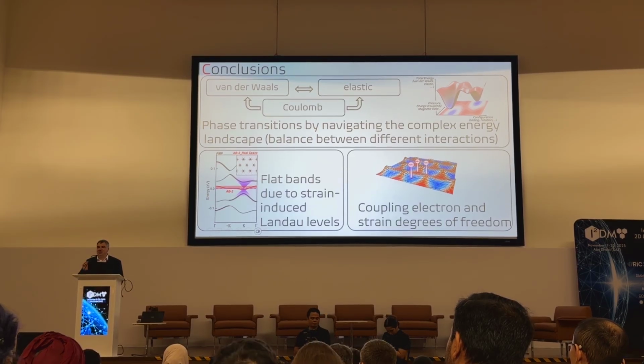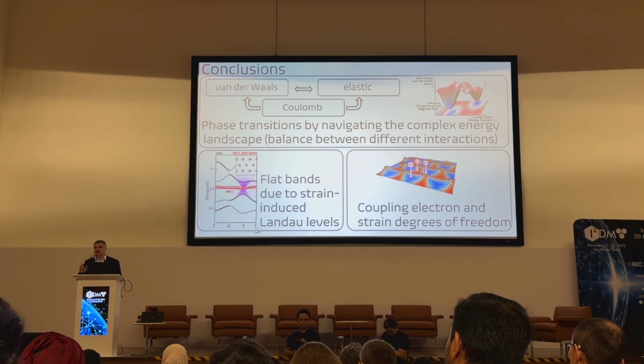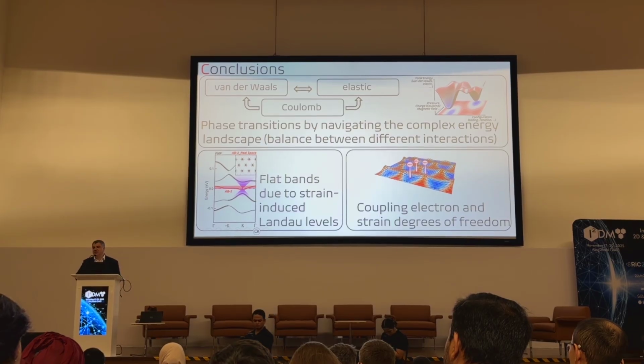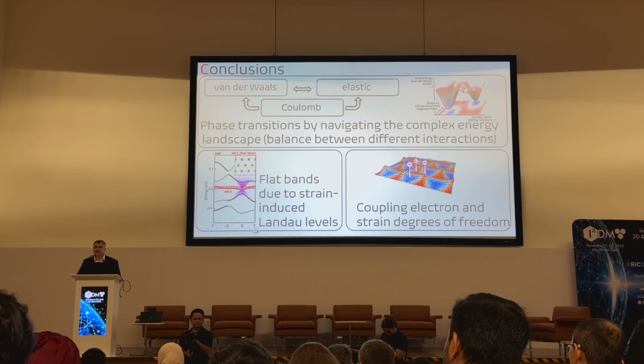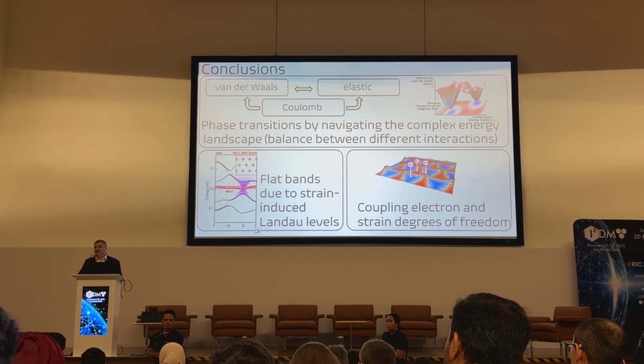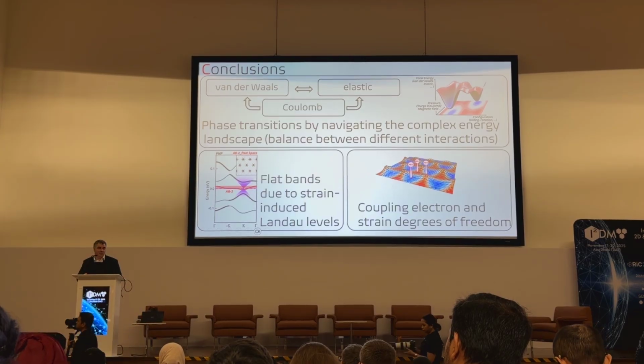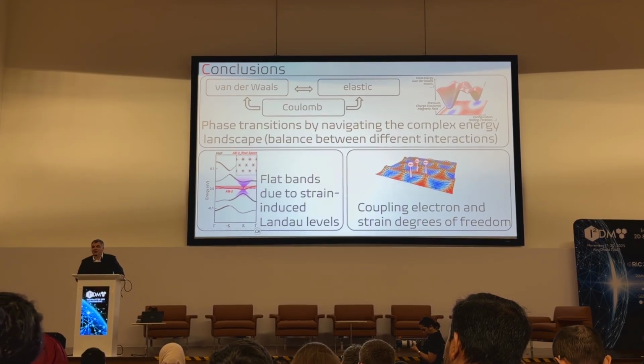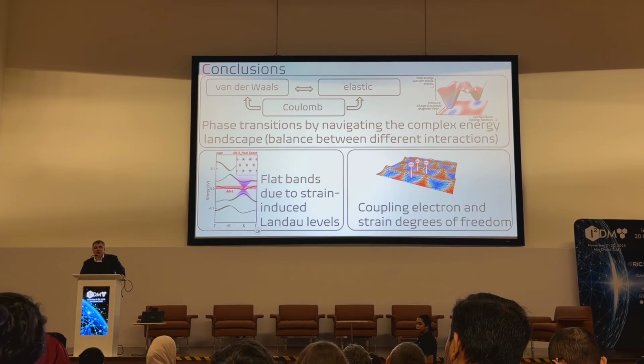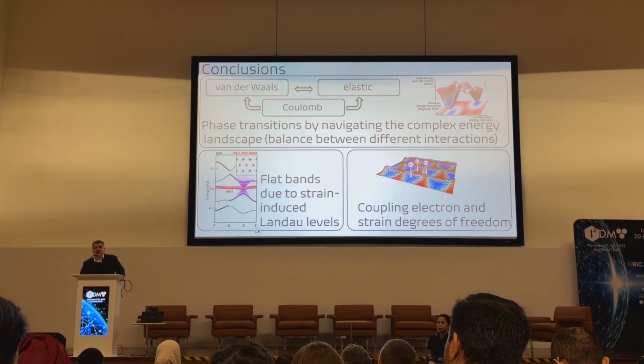Typically, those twisted defects would be very sensitive to the displacement electric field, which we see from the work of other groups, also in other cases. This effect is not sensitive at all to the displacement field. So we know that it's not coming from one of the interfaces. It's purely Coulomb interaction. Now the second question you mentioned is the scalability.